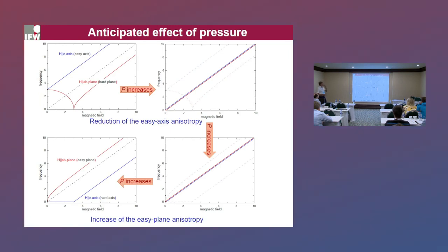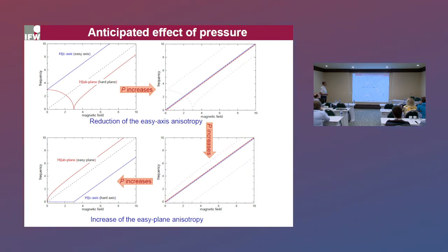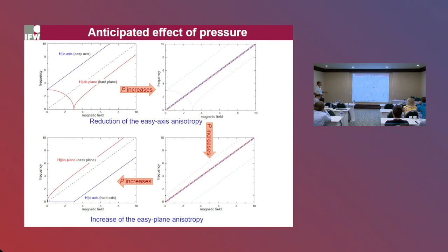The final question of interest was how to change the magnetic anisotropy, since having a handle to tune these important magnetic properties would be significant. One possibility is to apply hydrostatic pressure. We thought we could observe this through changes in the ferromagnetic resonance. In the absence of pressure, the two excitation modes have different energies due to the magnetic anisotropy. By increasing the pressure, it might happen that the anisotropy decreases and these modes merge into a single line, and possibly even the type of anisotropy could switch from easy-axis to easy-plane.